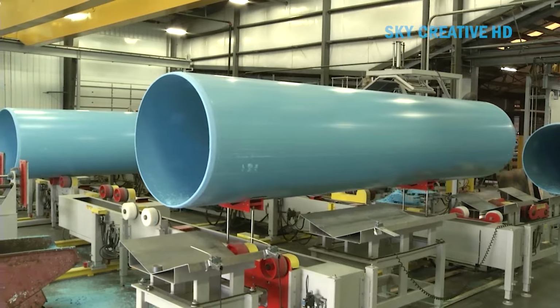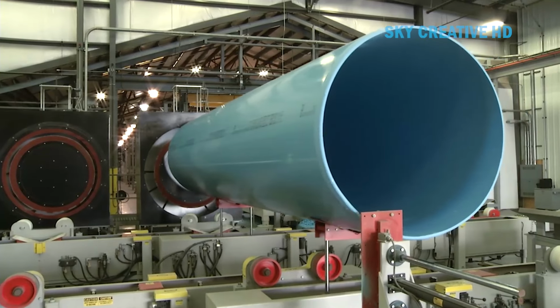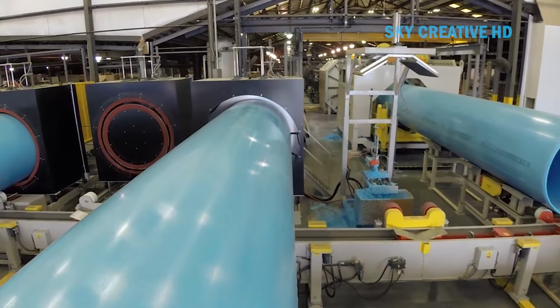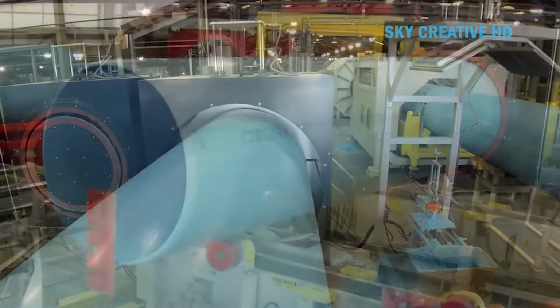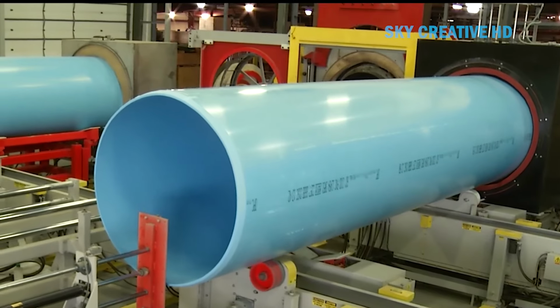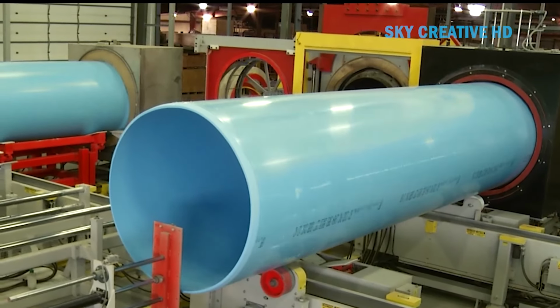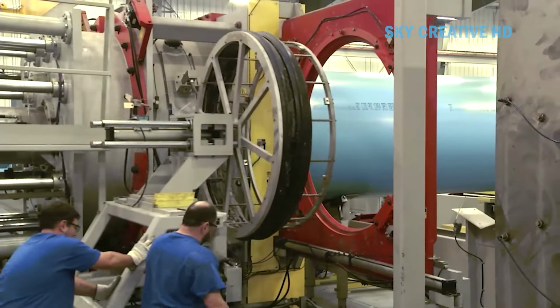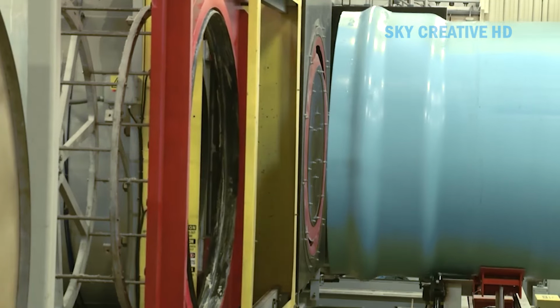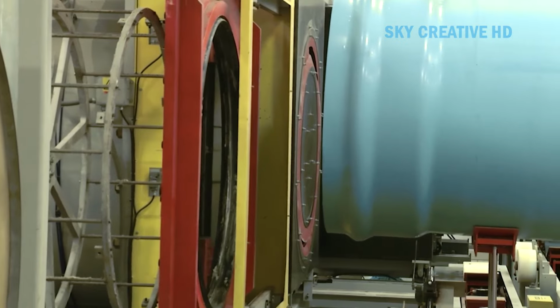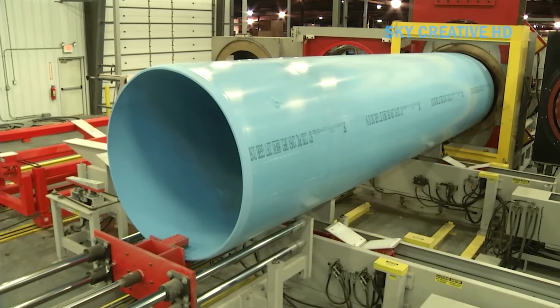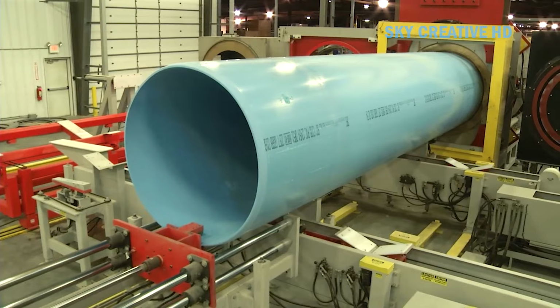Here's where it gets impressive. The molten PVC exits through an enormous die head, a precision-machined steel ring that shapes the pipe's profile. For a 54-inch pipe, this die might weigh over a ton. The die includes internal mandrels and external rings, creating both the inside and outside diameters simultaneously. Die design is critical. It must account for die swell, where plastic expands slightly after leaving the die, and ensure even flow distribution around the entire circumference.